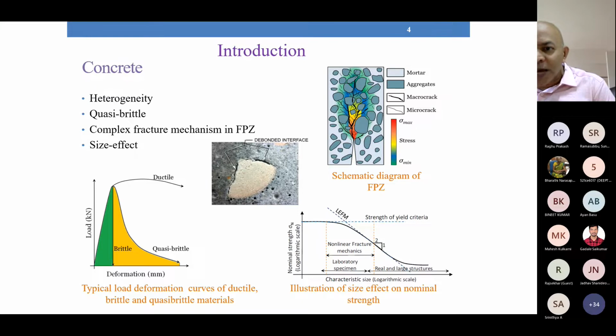And also, there are a lot of micro cracks in the mortar in front of the crack, in front of the true crack. These aggregates, the large aggregates, will provide resistance to the crack propagation, and the crack has to go around the aggregate, or sometimes it passes through the aggregate. So crack branching takes place. So the crack path is not a smooth path. It is a very tortuous path, okay, containing this bridging of aggregates and so on. So a lot of toughening mechanisms occur in this fracture process zone.